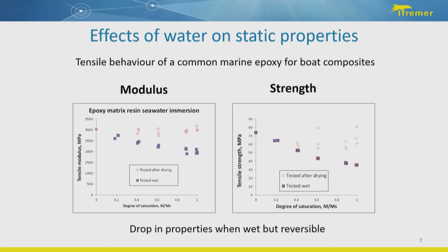So that is the immediate effect on the properties of the material, how they've changed when it's working in water. But the good news is that for these materials, it's a reversible change. So when you dry them out, then you can recover most of the modulus and most of the strength. So it's a plastification effect rather than a degradation effect. If you leave it a longer time, then you'll start to get degradation.